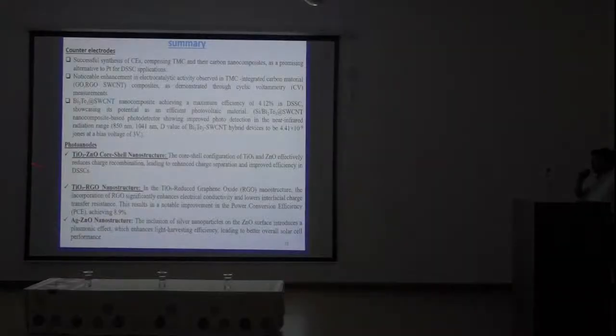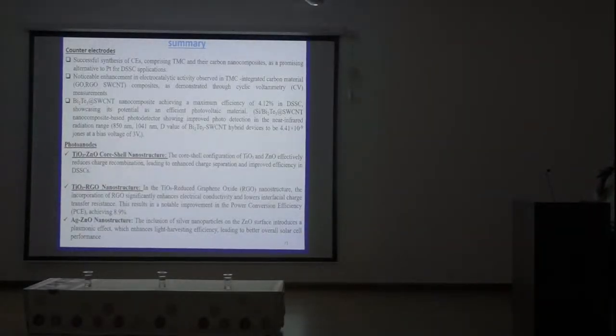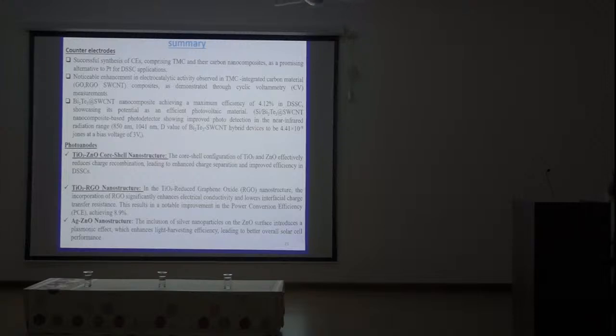And on the photoanode side, we have used TiO2 ZnO core-shell nanostructure, TiO2 RGO nanostructure, and Ag nanostructure. With TiO2 ZnO, the charge separation is increasing because the ZnO acts like an energy barrier to improve the charge injection efficiency. And with the TiO2 RGO nanocomposite nanostructure, we are getting improved charge transportation. The RGO is providing more electron transport channels to improve the